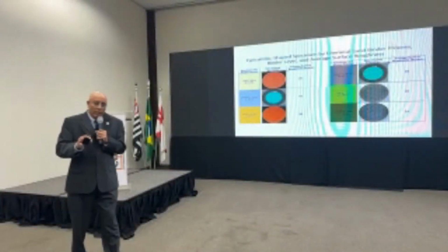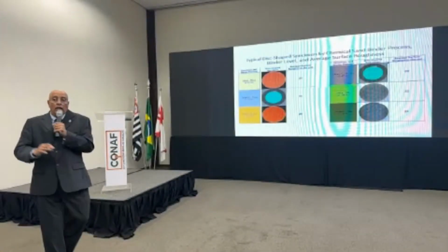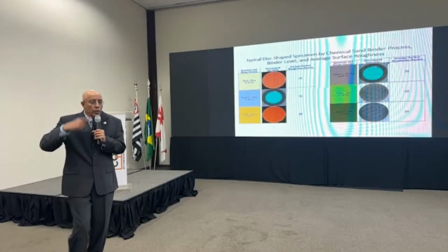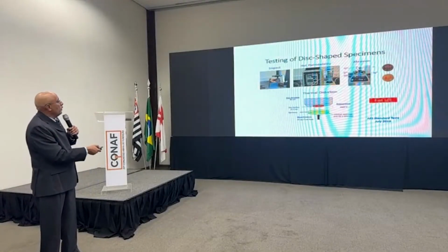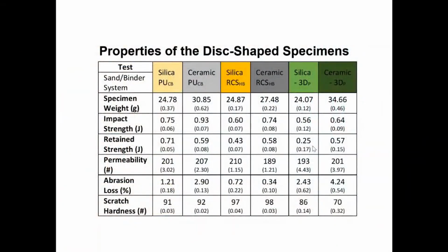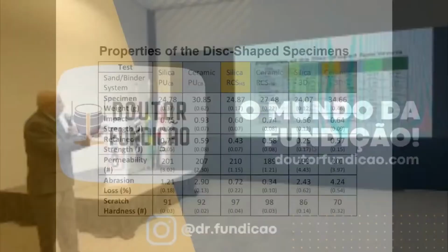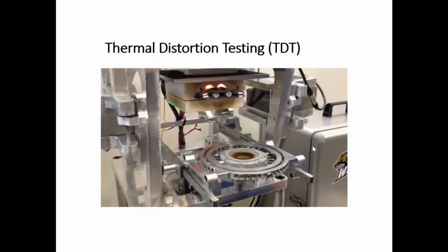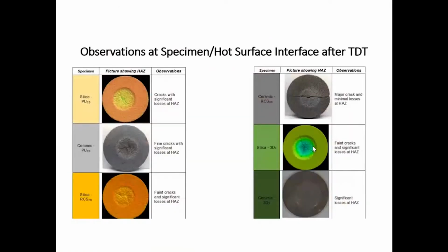So we measure. As I mentioned to you, when metal touches the surface, it should get better, meaning we get a lower number. If the number goes higher, we know we have a mold-metal interfacial reaction. So look at what is happening. We perform these tests that I showed you before. We have the data. I can share this data, or the Curimbaba group, Mr. Peter, can share all this data we have given him, save us some time. We have run the thermal distortion test like I showed you before, and we got all the laboratory data. Here in the silica sand, the ceramic sand, you see what's happening.